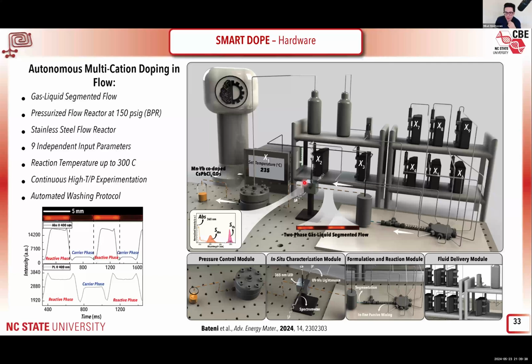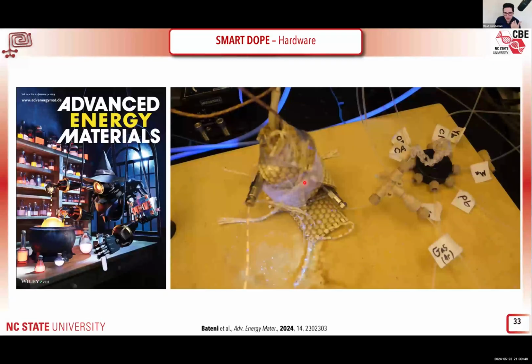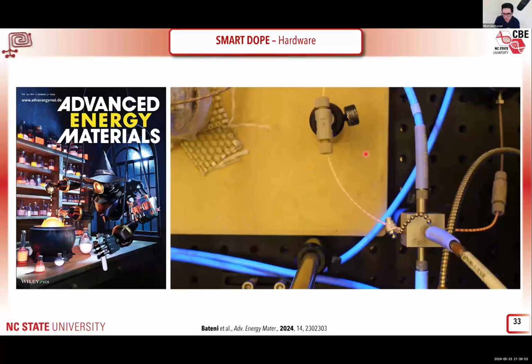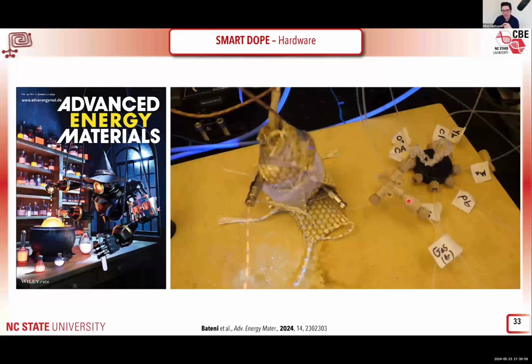So here's a video of this operation, mixing, segmentation, and the synthesis happens in this high-temperature reactor that you can't see because it's thermally insulated. And here is the product leaving the reactor. This is a gas-liquid segmented flow, argon and liquid segments. This is cooled down to room temperature, goes through our in situ spectroscopy module, and we characterize the product. The data goes back into the AI agent.